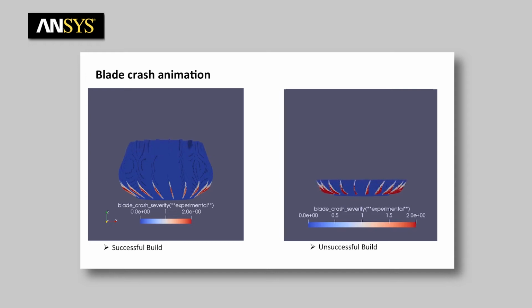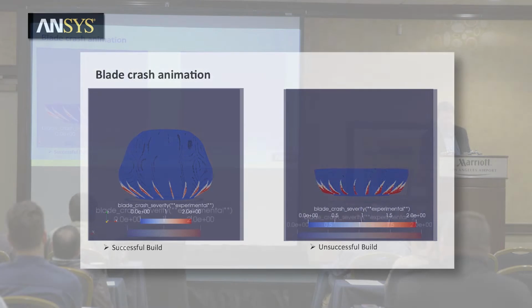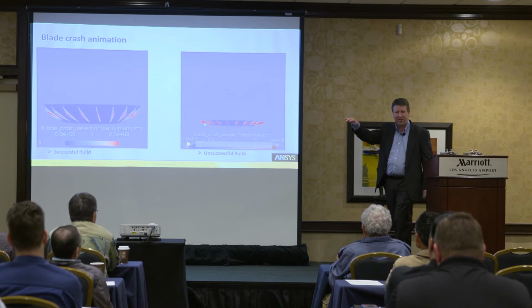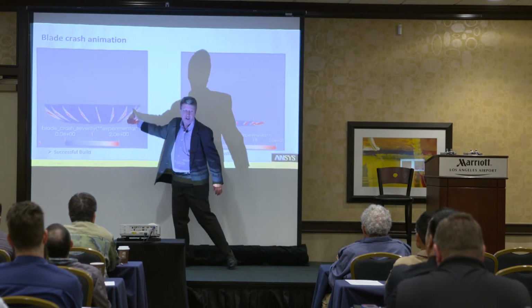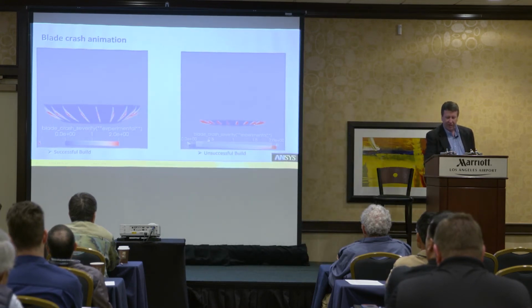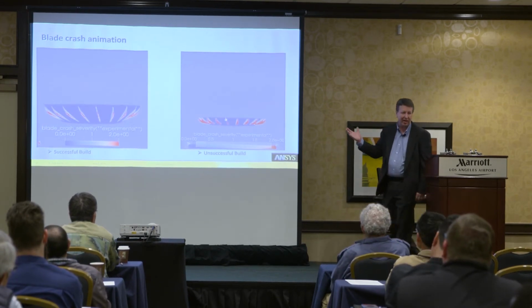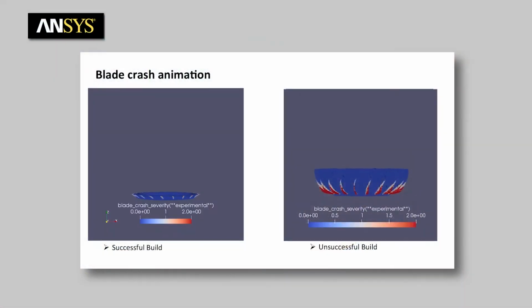They had one design they also tried to build that we did here, where the entire blade was sticking up. You can see that the angle here is much sharper, rather than this, which is sloped up at much less of an angle. And so this one actually smashed the blade and actually failed. They had to kill this build, and it wouldn't complete. And our simulation also showed the difference between the severity of that. And they said, sure enough, yeah, what was happening over here, that's too much. It killed, but over there, just a tiny bit of the edge, and it was okay. It can kind of bump over top of it and keep building.